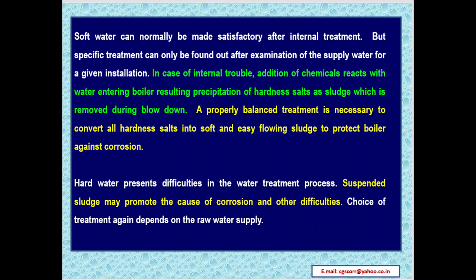In the case of internal treatment, addition of chemicals reacts with water entering the boiler, resulting in precipitation of hardness salts as sludge which is removed during blowdown. A properly balanced treatment is necessary to convert all hardness salts into soft and easy flowing sludge to protect the boiler against corrosion. Hard water presents difficulties in the water treatment process. Suspended sludge may promote corrosion and other difficulties. Choice of treatment again depends on the raw water supply.